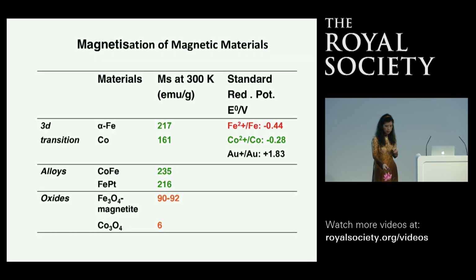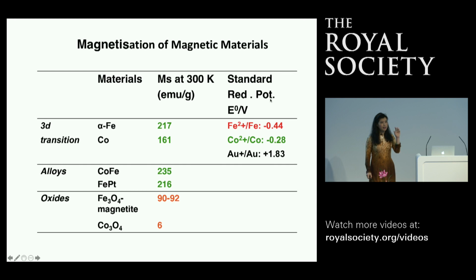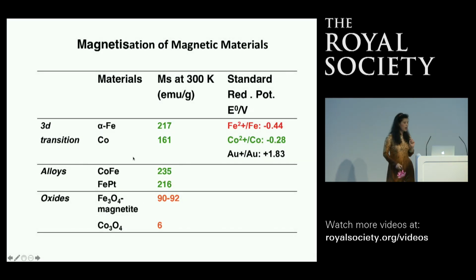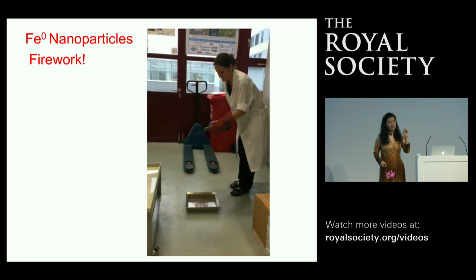Because pure iron has a very negative standard reduction potential. That means that this iron will get oxidized very easily compared to gold nanoparticle. 3,300 years ago, the Tutankhamun mask is still bright of gold, but no way can it keep anything of iron for that long. So then we can also have different kinds of alloy in between, okay? When I started my research in magnetic materials, when you're young, you're a little bit more ambitious. They say, okay, go and get something the most magnetic. Iron was too difficult, I knew that. So I just tried to understand why it's so difficult, because it oxidizes so easily.